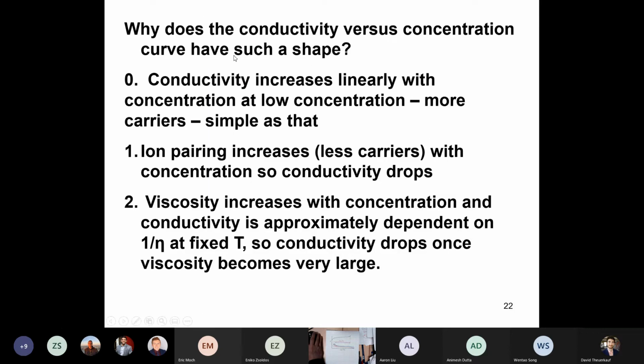So why does the conductivity versus concentration curve have such a shape? Conductivity increases linearly with concentration at low concentration because you have more carriers, more ions in solution. It's as simple as that. And then people say that as the concentration increases, you get what's known as ion pairing. That means there are fewer carriers with concentration, so the conductivity drops. I want to spend a moment on my document camera just talking about ion pairing, just so it's clear to everybody what's going on.